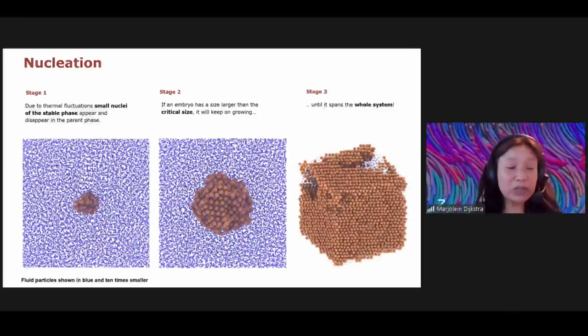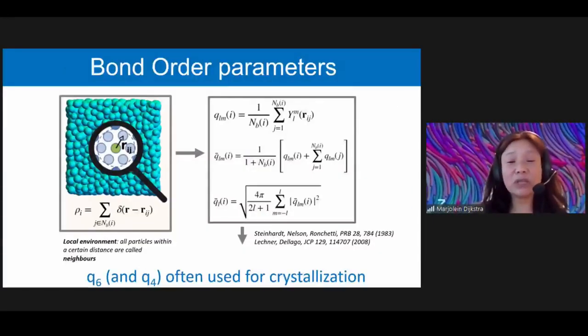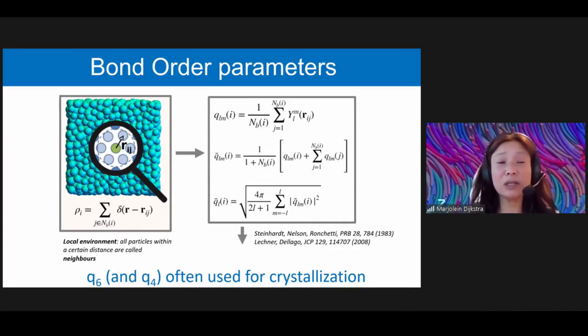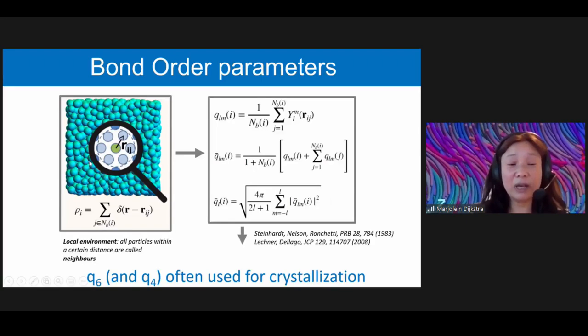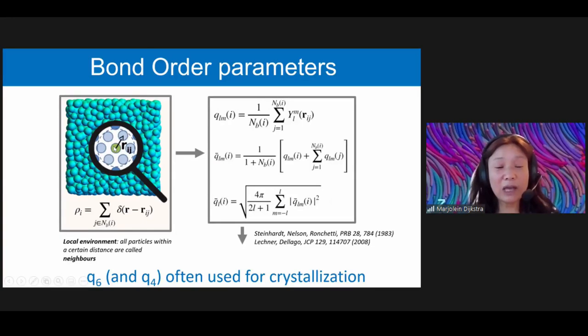And in these pictures, I already show you the fluid particles 10 times smaller, and I denote them in blue. And so if you want to study nucleation in such a system, either by experiments or by simulation, it would be very nice to have an algorithm or an order parameter that can identify on a local particle level in what environment such a particle is. And for that, we often use the Steinhardt-Nelson bond order parameters. You first identify the local environment of a particle. You identify all the neighbors of, for instance, this green particle here in the middle. And that can be done, for instance, by a simple distance criterion or a Voronoi construction or more involved algorithms.